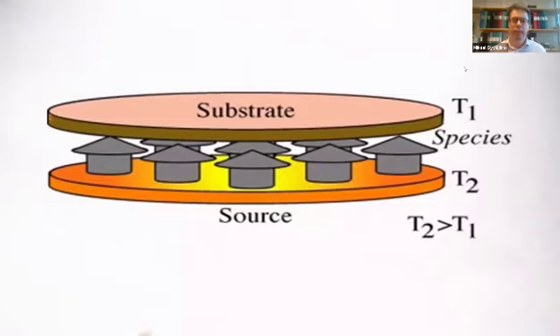And what we did was that we explored this PVT method in general. And then we made some modified approaches. And one of them is that we decreased the distance between the substrate and the source material to shorter. And then we also lowered the growth temperature. So then we could not grow the thick bulk, which was the original aim, but we could use the high growth rate to grow thick layers of silicon carbide.